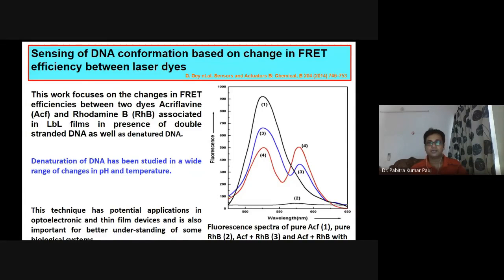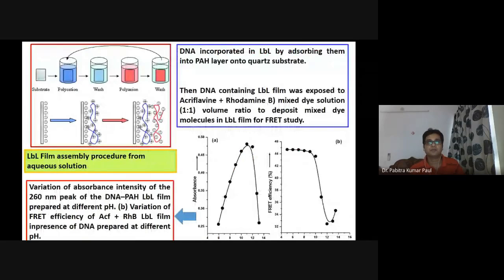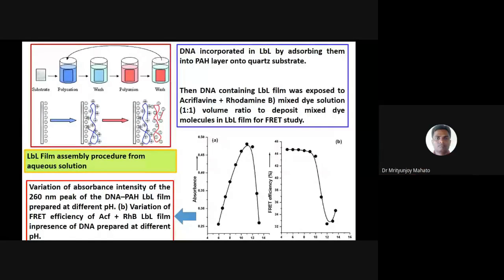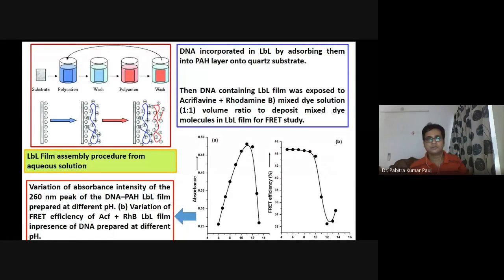So this highlights some results. This is the fluorescence spectra of the acriflavine and rhodamine B mixture in solution and in LBL films. And this is the technique of preparing the LBL film, where the polycation and the anionic substance are alternately deposited on a solid substrate, and we have measured the DNA absorption. You know, the DNA has an absorption peak at 260. So this is the variation in absorption intensity with respect to the pH, because we have changed the pH of the DNA solutions, and we see that this is maximum.